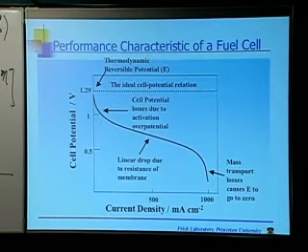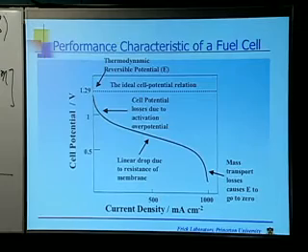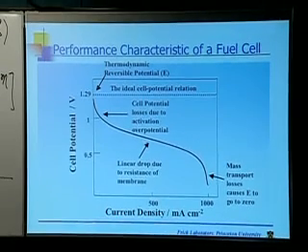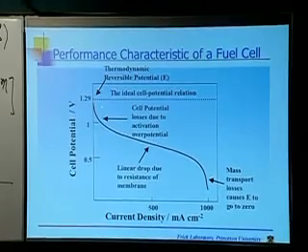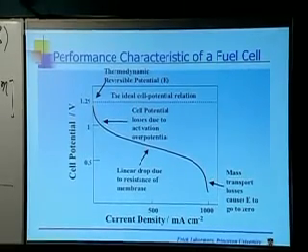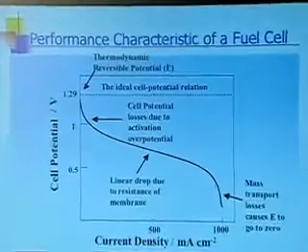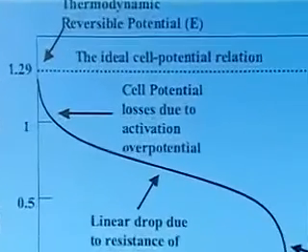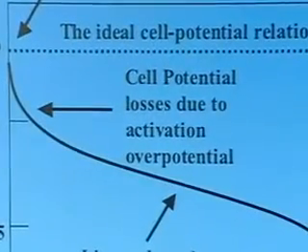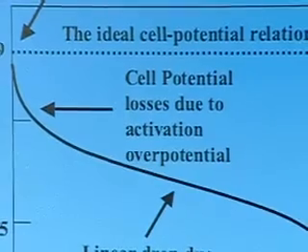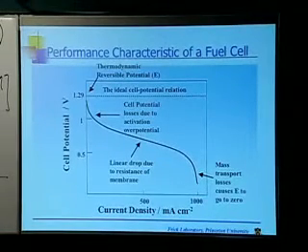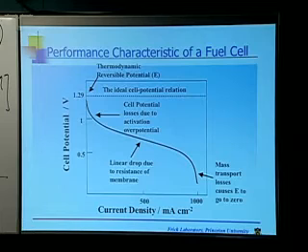This is the Tafel part of that curve. This is exactly this relationship right here. That drop-off in potential is due to the overpotential for carrying out this reaction. Now, it turns out on a well-prepared platinum surface, the overpotential for hydrogen and protons is really small. In fact, negligible compared to the overpotential for the oxygen reduction. So we're seeing about a 400 millivolt drop-off in this region, and just about all of that can be attributed to